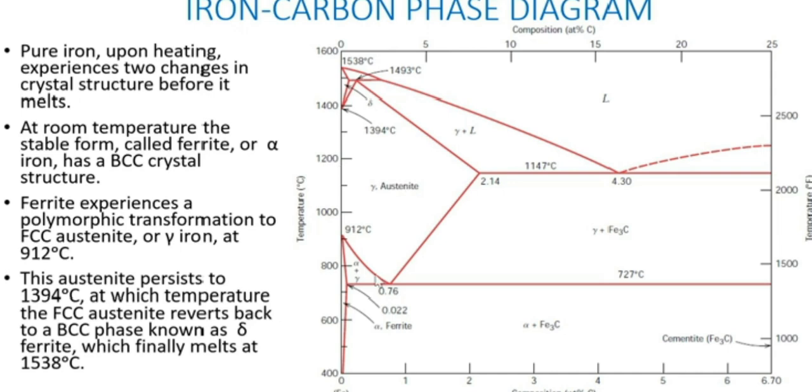So next we look at the iron carbon phase diagram. Here you see we have the alpha region, which is only a solid solution. It means the carbon in this small region alpha is soluble, isn't it? As you move from this region to here, the carbon is no more soluble, so it will appear as what? Some carbon atoms are soluble in alpha, but anything above 0.022 will not be soluble in alpha.